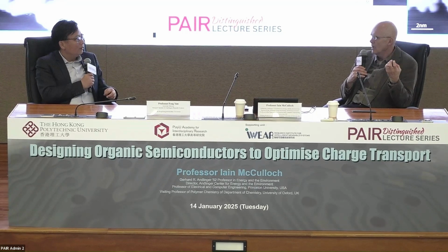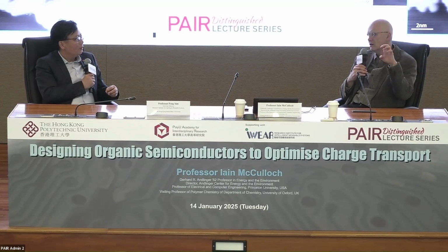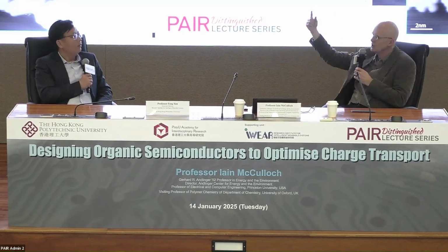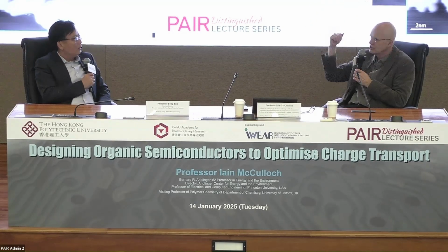So that's a very simplistic view. And then you think about, in terms of polaron injection, how you can maybe have a backbone that has a very low reorganizational energy or very low disorder on injection, and that gets to quite a high level of packing. So if you can introduce interdigitation, that reduces the swelling, and we did that through short chain, long chain effects. Interdigitation is much harder in OECT materials, as I showed you, because of the glycol, the helical conformation of a glycol chain. It's harder to force interdigitation. So if you don't have the interdigitation, you get a much higher degree of swelling.